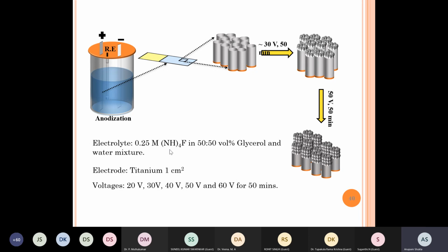Okay, so what we did in our lab was to look at a titanium-based pseudocapacitor. So this is TiO2. Essentially, we start with a titanium metal foil, do an anodization of it to generate pores on it, and these pores are titanium oxide. When we anodize it, the pores are formed of titanium oxide, and this is well known. This is used for preparing some microfiltration membranes for gas separation. But what we did was that we tried to do some modification here so that these smooth pore walls are made into rough pore walls. And when you make rough pore walls, then the area of the pores will increase, and therefore it is possible to have more capacitance in the same geometric area. So that is in schematic what we tried to do in preparing this pseudocapacitive electrode.